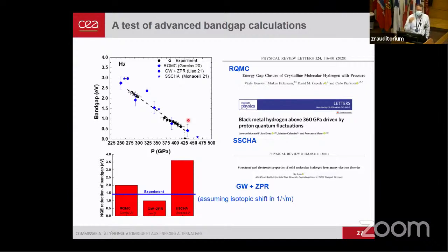I should say that if you do the best DFT calculation without taking into account the coupling between the nuclear quantum effect and the electrons, you have a gap which is much higher. In all these calculations, it's the quantum corrections on the proton that reduce the gap. The quantum Monte Carlo, which is the most advanced, gives a 2 eV reduction, and the others give 1 and 3 eV. And for our measurements of H2 and D2, since we make them at the same pressure, the shift is quite accurate, we believe. Assuming the isotopic shift goes as 1/square root of m, we have a reduction from this effect of 1.5. So that is a reasonable agreement with the most advanced calculation.